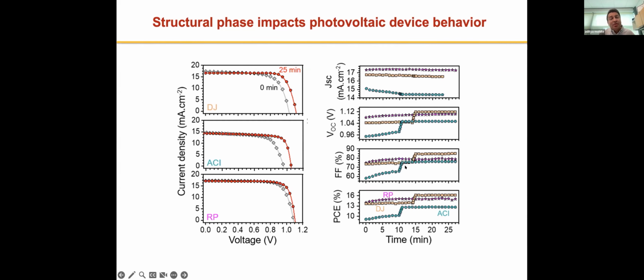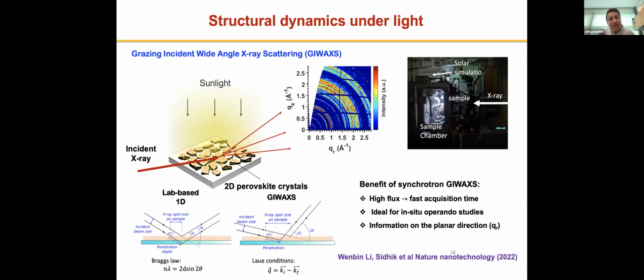And so at that time we thought that this was some sort of a measurement error or some kind of a circuit issue that we were undergoing. And so, after having my student repeat this multiple times, we finally concluded that this was really real. And so this is where we wanted to really understand what's really going on and understand the structural changes that may be undergoing when we expose this to an AM1.5 solar simulated light. So we of course contacted Joe and we set up this experiment where we looked at the powders of the 2D perovskites, we looked at films of 2D perovskites, and we also looked at single crystals of 2D perovskites.